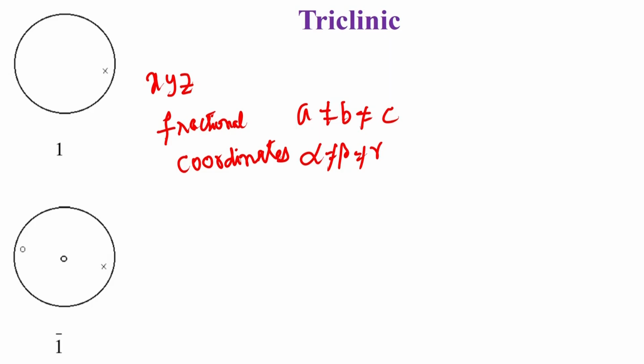So, these are referred to as fractional values of A, B and C. Normally the x value will appear as, let us say, 0.1, which means it is 0.1 of the length A. So, the fractional coordinates are representations of the 3-dimensional coordinate system in the given crystal system. If the system is triclinic, we have this way of representation, that is to say x, y and z now represent fractions of A, fractions of B and fractions of C.